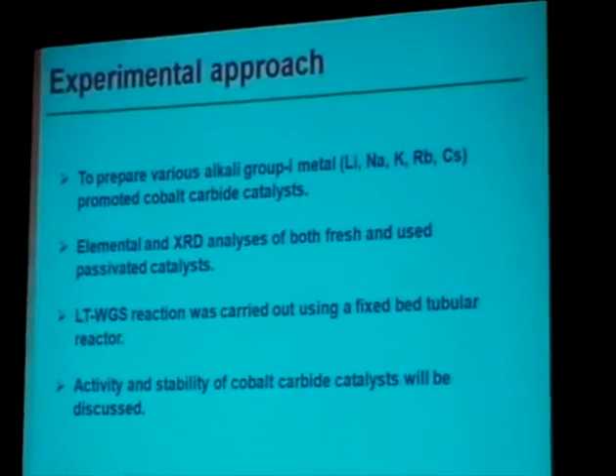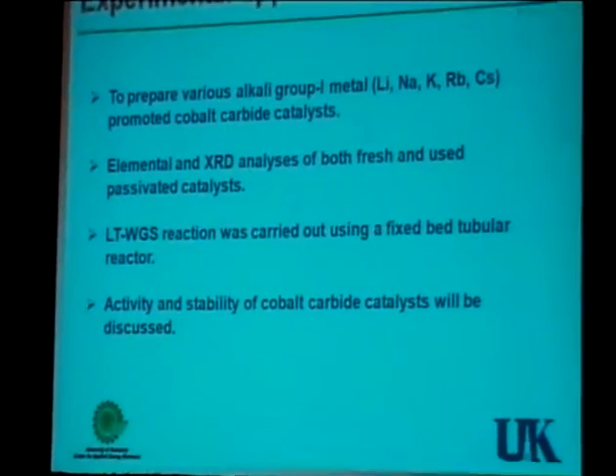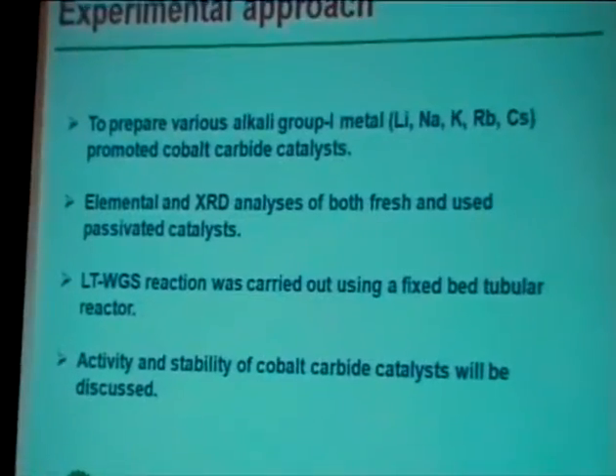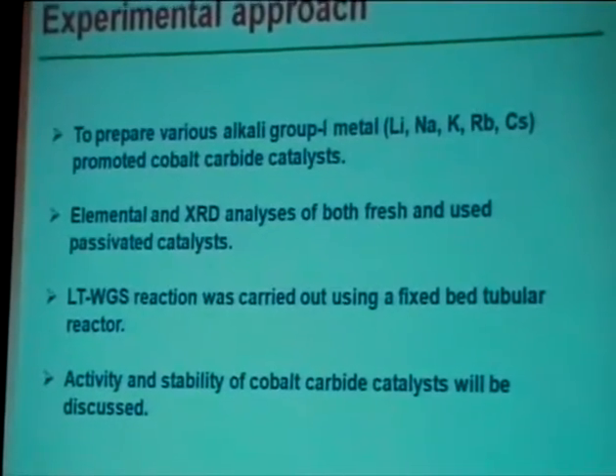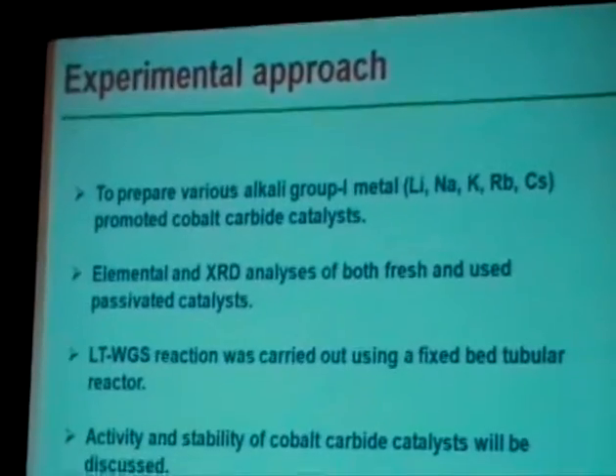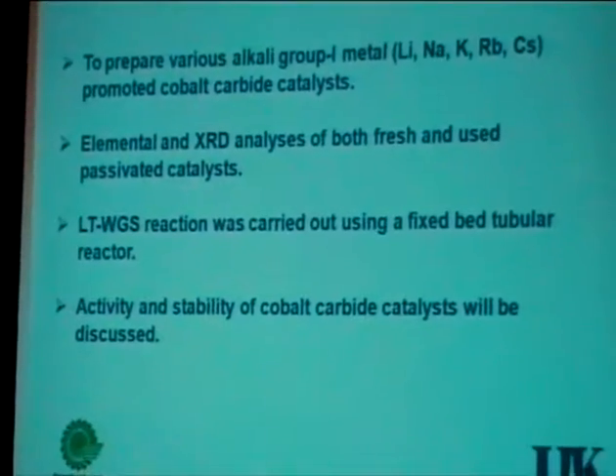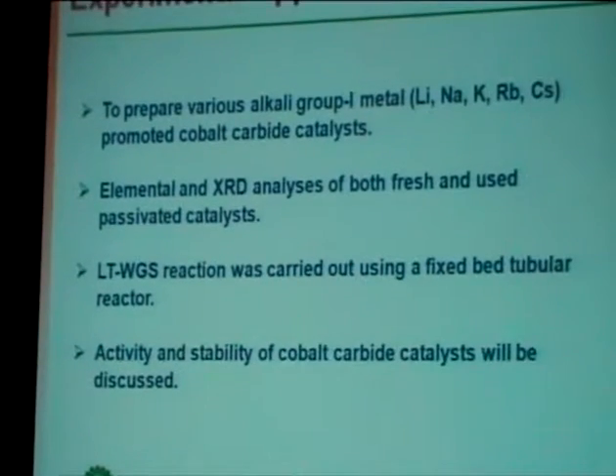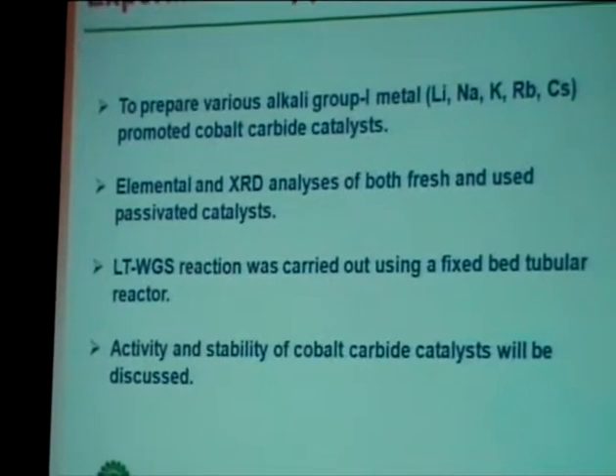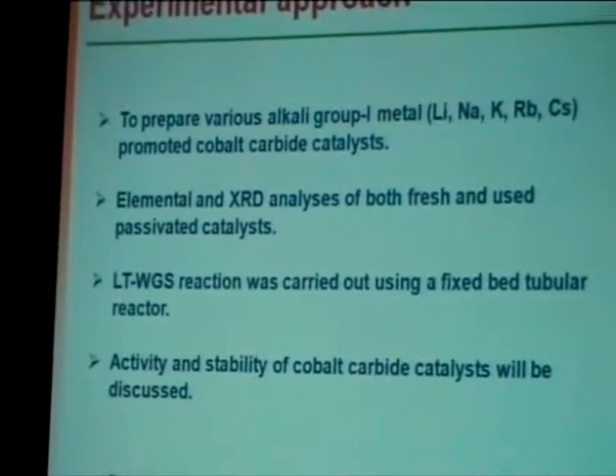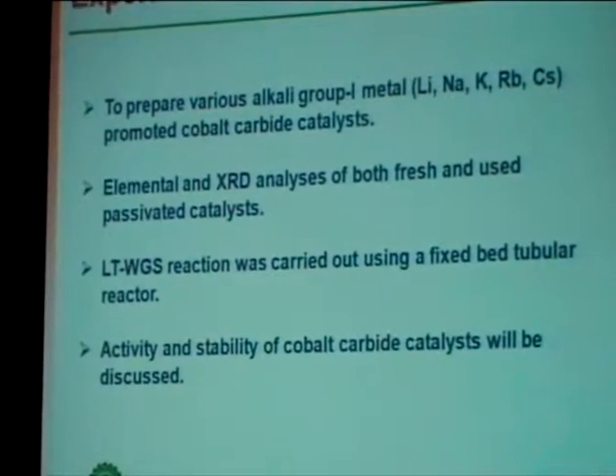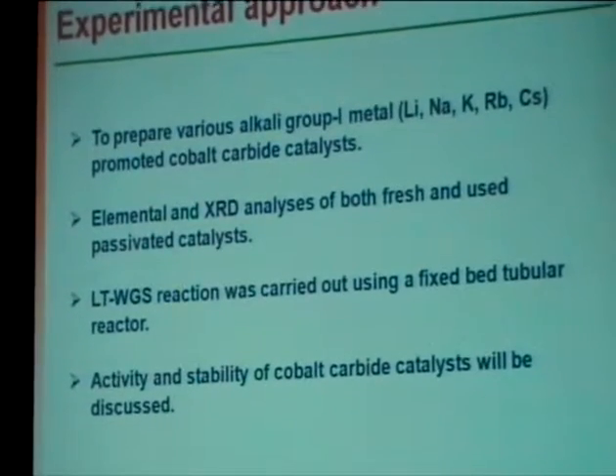So what we actually did is we tried to prepare the cobalt carbide, promoting with alkali in order to increase the water gas shift activity of the carbide and see how stable it is under the water gas shift conditions. And we did an XRD analysis of both the fresh and the spent catalyst after being passivated with 1% oxygen in helium, and being characterized. And we are trying to see if there are any phase changes that occur during the run. And then we did this reaction in a fixed bed tubular reactor,